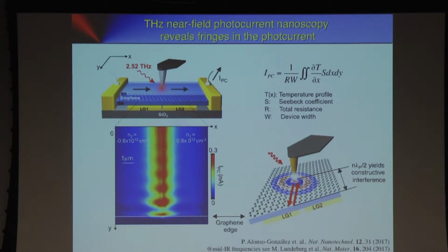That's the first problem. And the other problem is that detectors in the terahertz spectral range are typically bolometers, but bolometers are very slow. And remember, we oscillate the tip and do higher harmonic demodulation at several hundreds of kilohertz, and that is not really good for bolometers, so they cannot detect this light. And anyway, scattering efficiencies are weak. So that's a problem. This is why this technique evolves very slowly.